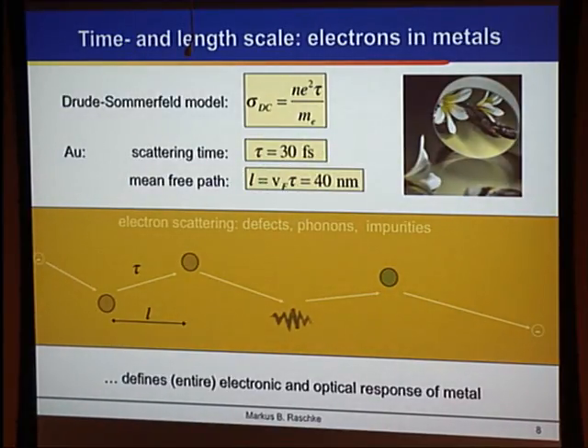And then you find that you typically have electron-electron interactions, or electron-lattice scattering, or defects or phonons, on the order of 30 femtoseconds. And if you know what the Fermi velocity is, equivalent to about 10,000 Kelvin of electron temperature, then you can see that these interactions occur every 40 nanometers on statistical average. And so it's really this elementary time and length scale which defines the entire electronic and optical response of the metal, and this tells you that this is what we would like to probe in a generalized fashion.